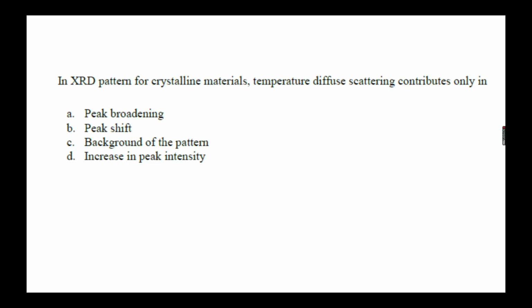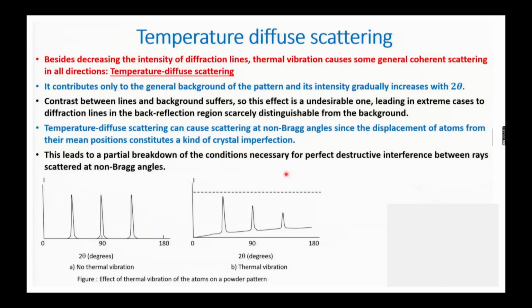Okay, fine. So the answer is C, background of the pattern. As you can see in this XRD plot, in XRD what we usually get is intensity versus 2 theta. Here it is showing no thermal vibration, and here some thermal vibration. It shows the effect of thermal vibration of the atoms on a powder pattern, and these XRD peaks are showing that.